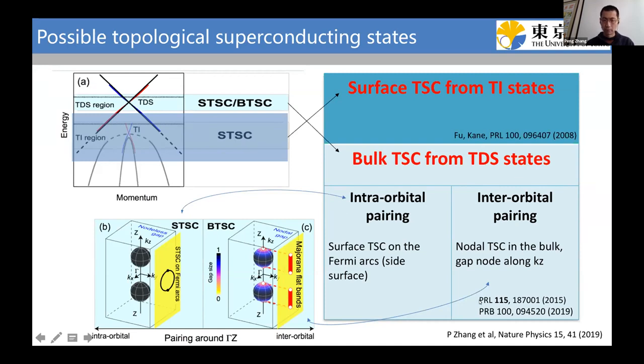But in this paper, the authors found that for the topological Dirac metal, there is a special orbital pattern because of the p-d hybridization near the Dirac point. This orbital pattern will favor interorbital pairing. In this case, we can expect a nodal gap along the kz direction. It's a triplet pairing, and on the side surface, we will have Majorana flat bands.